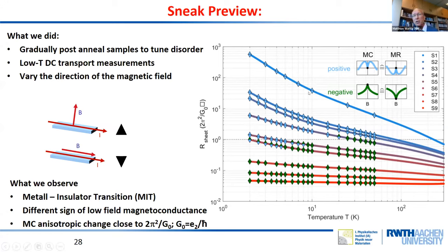But there's a second message in these curves here, and this is the sign of this direction of the triangle. So this here is the perpendicular magnetoresistance, and this here is the in-plane magnetoresistance. And we have two different signs. We have either a positive magnetoconductance, this is the blue color, or we have a green color for a negative magnetoconductance. And you see that linked with this MIT, there's a transition from the blue to the green arrows, which is a transition from a positive to a negative magnetoconductance. So we change the sign of the magnetoconductance at low temperatures and low fields. So MIT and magnetoconductance sign change.